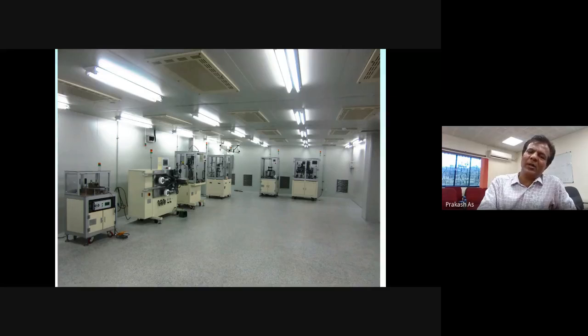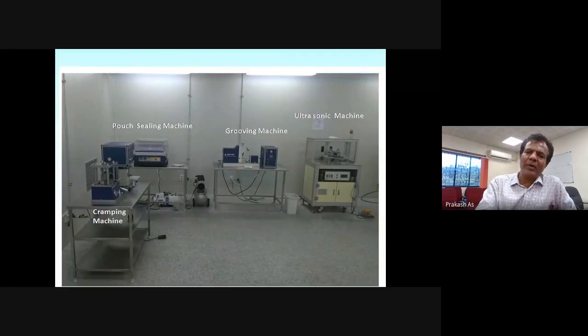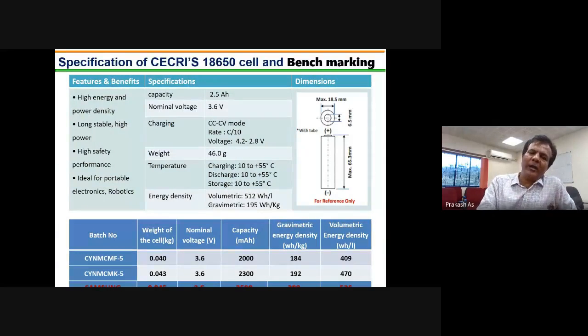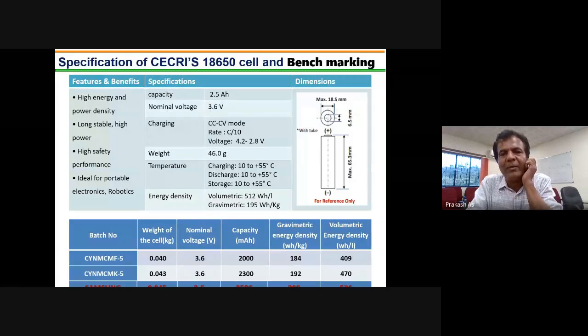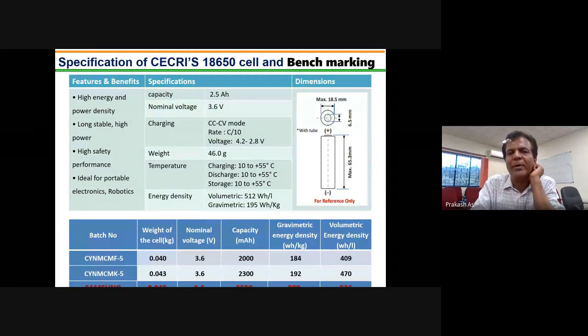And we make this kind of 18650 cell, and these are the specifications of the cells we prepare. The batteries we prepare in our lab are about 2.5 ampere hour and 3.6 volt. And these are the charging conditions. Weight of these batteries is 46 grams. These batteries can be charged at temperatures of 10 to 55 degrees centigrade, and discharging is also 10 to 55. And storage can also be done at 10 to 55 degrees centigrade. Energy density is about 512 volumetric and gravimetric is 195. So these are the specifications of the cells we prepare.